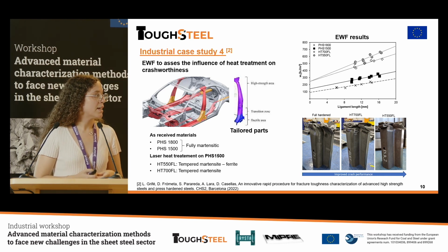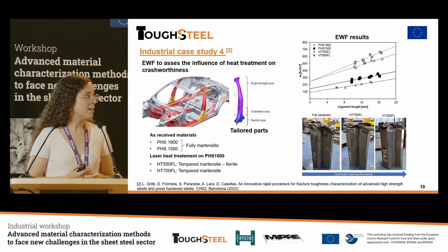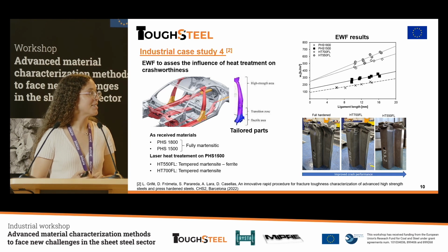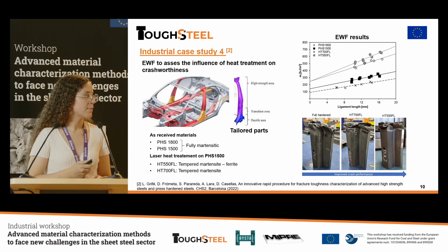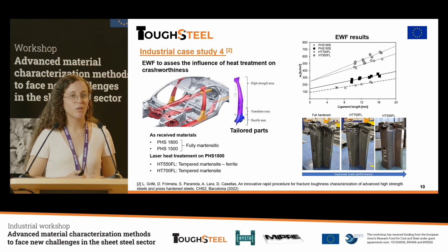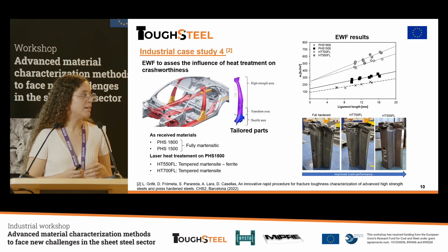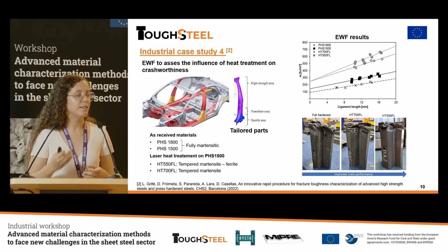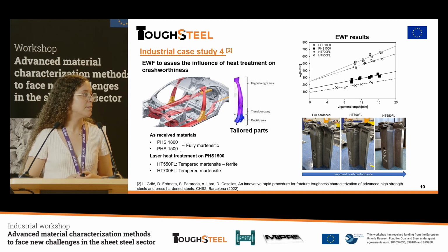So in this case, we performed tests with the PHS materials, 1500, sorry, with a fully martensitic microstructure. And then we also got material with two different heat treatments, one obtaining tempered martensite and ferrite, and the other only tempered martensite. When performing the essential work of fracture test, we could find that the crack propagation behavior of the materials with the heat treatment was really improved, and had a lot better performance in crash behavior as well than the material with the initial properties.